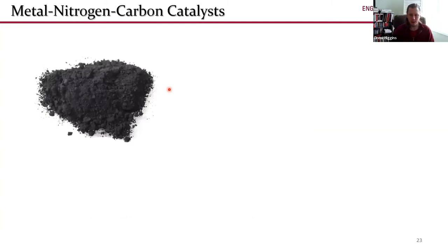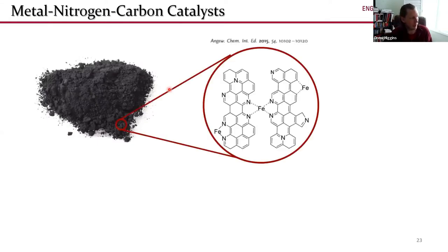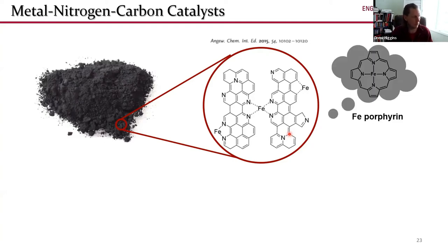And so now I'd just like to talk a little bit about a class of catalysts that I particularly find very interesting, and they're referred to as metal nitrogen carbon catalysts. To your eye, they essentially just look like a pile of graphite. You could take your graphite pencil, grind up that graphite into a powder. That is what these catalysts look like to us. But when you zoom into the atomic level, they have these transition metal ions coordinated to nitrogen dopants all within this graphitic structure. So it's big graphitic particles with these transition metal sites coordinated with some sort of nitrogen dopant or nitrogen ligand. And for any of you that work in the homogeneous catalysis space or molecular catalysis space, these catalysts have an active site structure that's analogous or very similar to some molecular catalysts we see out in the world, for example, like an iron porphyrin or something along those lines.